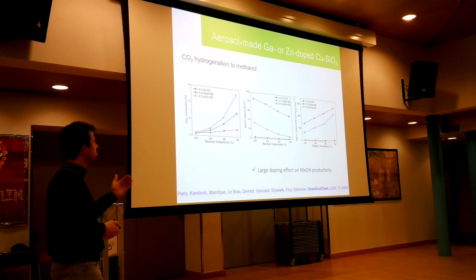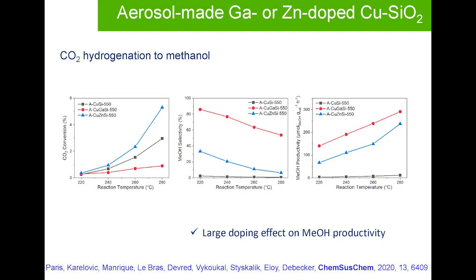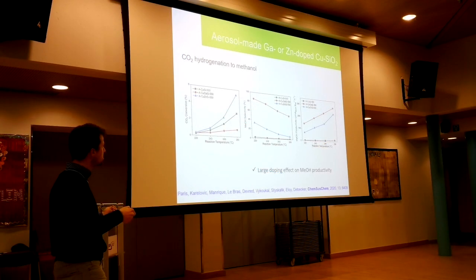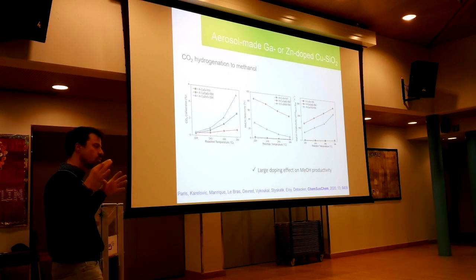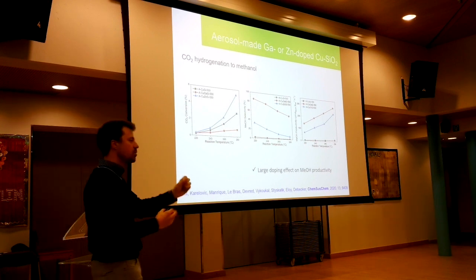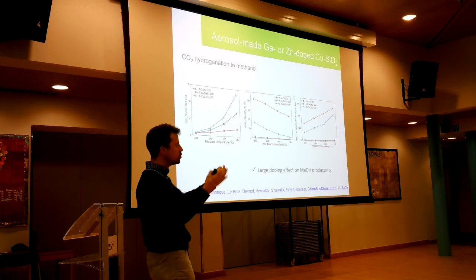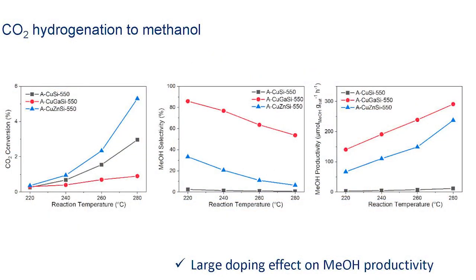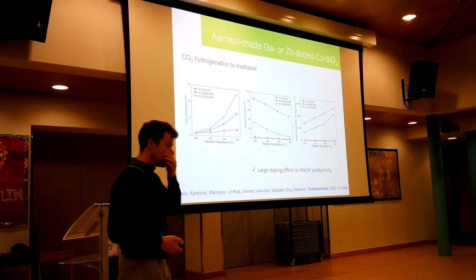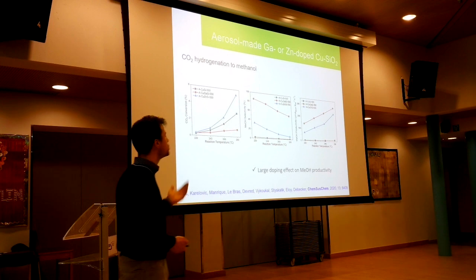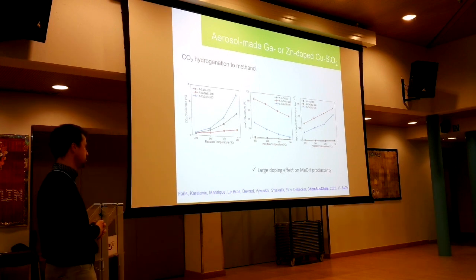The good thing with this system is that we could show a doping effect that was already known, actually, the doping effect of gallium and zinc that we put in those formulations. It's already known, but in these systems that are made in one pot with everything all together, with the copper that is really inserted into the gallium-doped silica, for example, the effect of doping was huge. In fact, the yield with copper silica is very low. As soon as you put a little bit of gallium or zinc, it's a huge doping effect that you get.